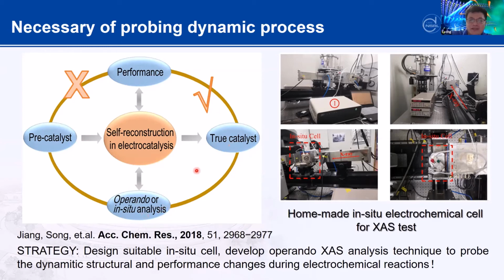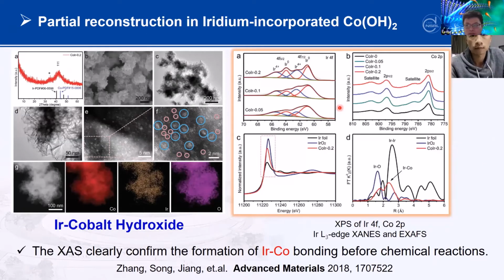That is why you need to design a very suitable in situ cell, and you need to develop operando XAS, especially hard XAS, techniques to probe the dynamic structure. And then you can build this performance relationship. This is just a picture of what we used for the XAS test. And these are examples. For some structures, as you can see, they do not totally reconstruct. They do not totally change phase. In most cases they just change the surface.